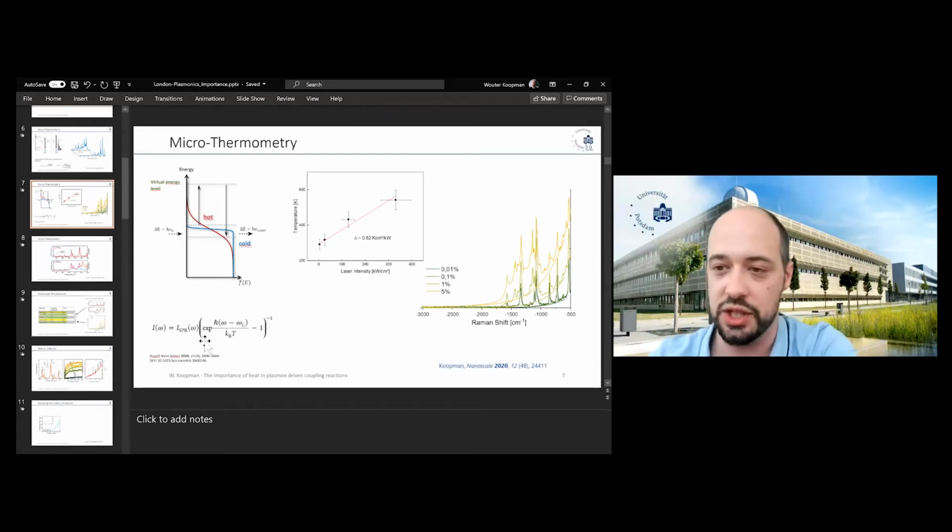The other thing, that's actually the way we have done it. The other way I found more recently in literature is people who just divided it by the plasmon resonance spectrum. But then actually not by the absorption spectrum, but you might know you can get a fluorescence spectrum from plasmonic particles. So you can get a recombination. And you have to divide by this recombination spectrum, because that is more or less the same thing, which also excites what really makes the enhancement, let's say.